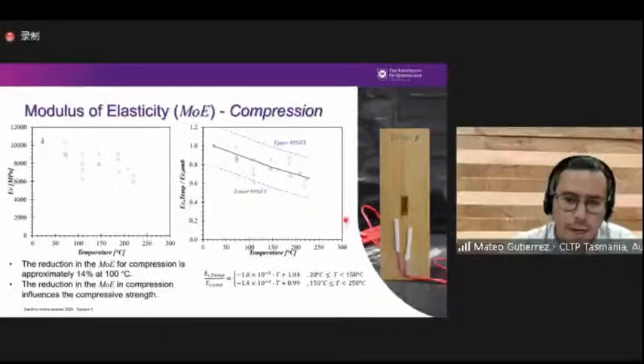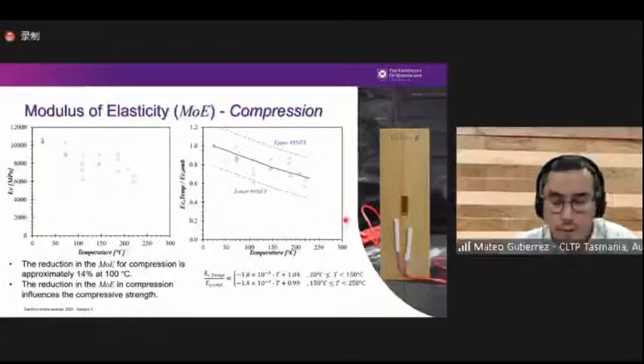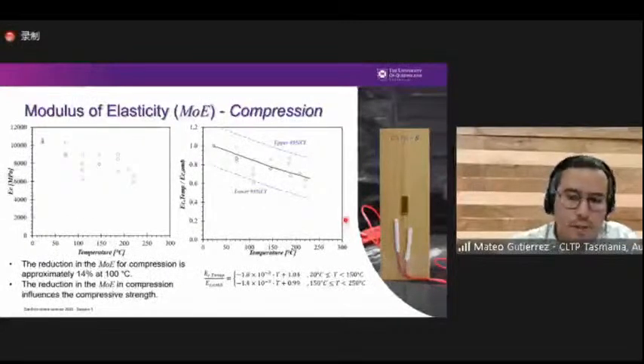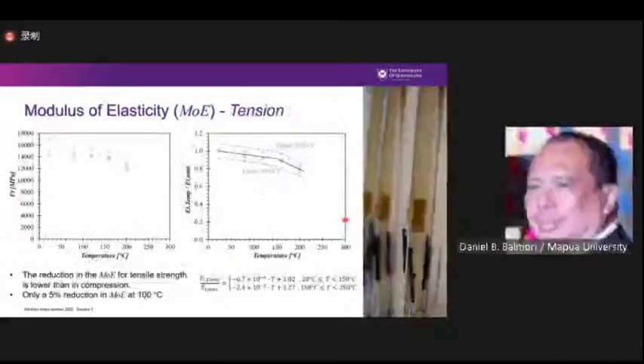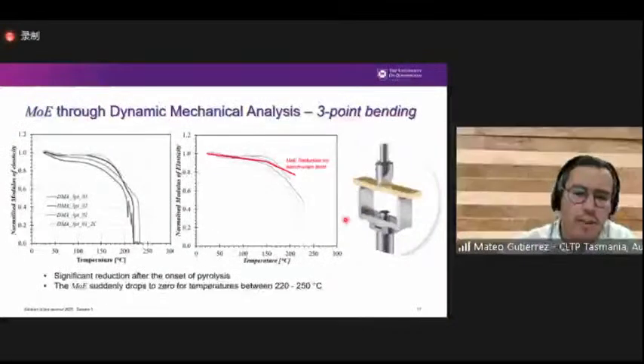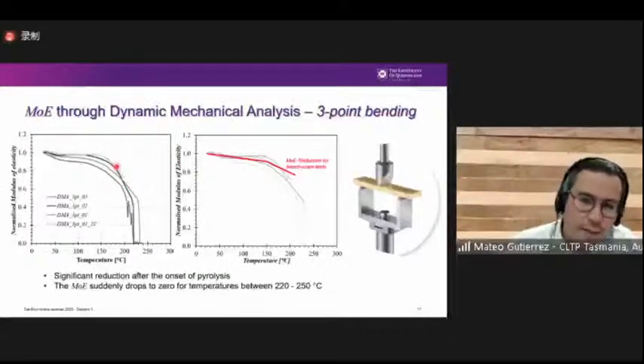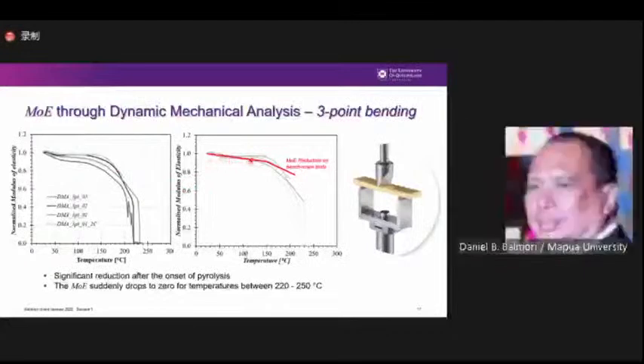We described the reduction in the tensile strength as well. We obtained some equations. When we were testing laminated bamboo in compression and tension, we also looked at the reduction of the modulus of elasticity. We used strain gauges, and we established some correlations between strain gauges and the displacement of the crosshead to obtain the reduction in the modulus of elasticity. And then we compared the results at this medium scale level against results from DMA tests. DMA stands for dynamic mechanical analysis, which is a very small scale test, but that can give us a really good understanding of the reduction of the modulus of elasticity.